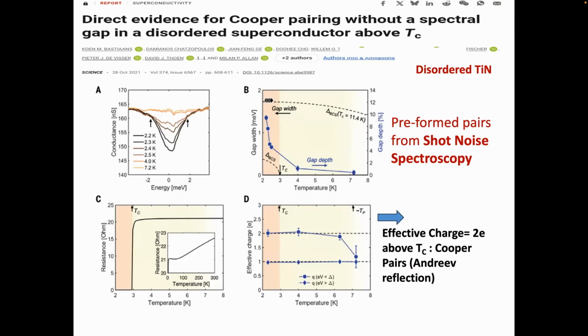But basically the idea is, the shot noise is how things clump up quantum mechanically. And so this experiment, according to Milan Allen's group and a couple other groups out there, argues that by looking at the shot noise, we can tell if the transport is 1e or 2e. So this is one where they're arguing that they can see that in this disordered titanium nitride, and I had the wrong element on the last slide, that they're seeing some effective charge 2e above TC in this particular disordered superconductor, which might be reasonable.